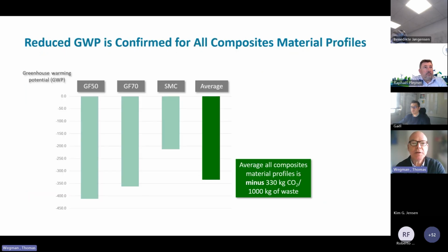But if I go to the individual materials, you can see there is a reduced CO2 savings. There's a reduced global warming potential. So CO2 savings confirmed for all these different material profiles. And that is a little bit more for the material which contains the higher level of resin. It is a little bit less for the SMC, which contains the calcium carbonate that is associated with that conversion of calcium carbonate that I was talking about. So if you take the weighted average of those three, you end up with the 330 number that we've used in the picture before.